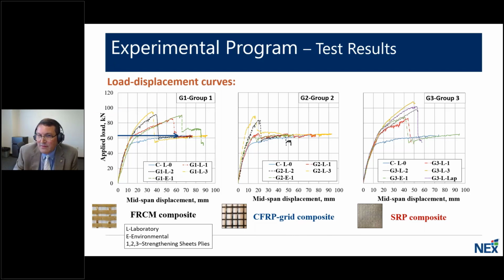And so when we look at the system in terms of one ply, a one-ply system again had a fiber rupture failure mode when looking at FRCM, while 2 and 3 plies debonded, and that occurred for 2 and 3 plies on the one-way slab. It may be noted again that the specimen subjected to the environmental conditioning provided additional capacity and additional ductility due to the post-cure effect of being in a moist environment as well as the temperatures in that environment.